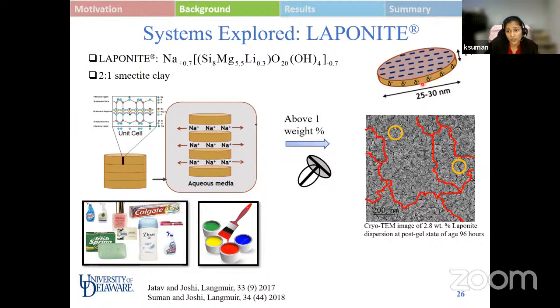Due to the charge anisotropy on each laponite particle, above a weight percent of 1, it tends to form edge-to-face attractive interactions, which give rise to a percolated network, as seen in the cryo-TEM image of laponite dispersion. The dark black lines are basically individual laponite particles, which can be seen to be very well connected, leading to a space-spanning percolated network, highlighted by the red line over here. Also, laponite is a widely used system in industrial products like paints and consumer care products, and as it's widely used in industry, it becomes important to study this system.